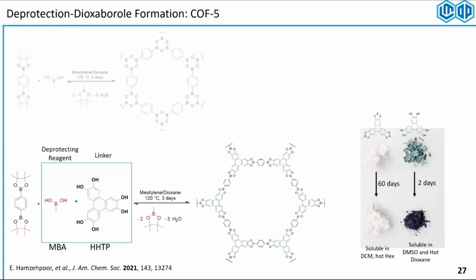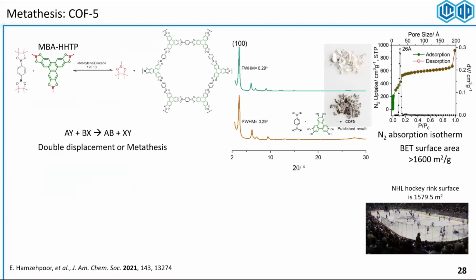And the product of that is indeed a very soluble compound, highly stable on the bench as well. And to our delight, that idea worked as well. So now we had a single precursor working both as the deprotecting agent and the linker for us. But what we noticed is it's fundamentally different from the bare boronic acid and bare catechol reaction, because that's a condensation reaction that occurs in the conventional synthesis. There's going to be water forming during the condensation, right? But our methodology was a double displacement.